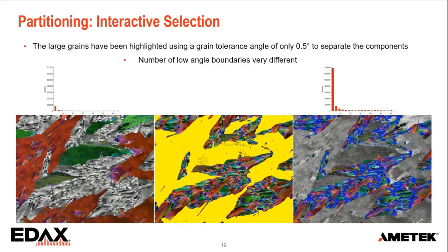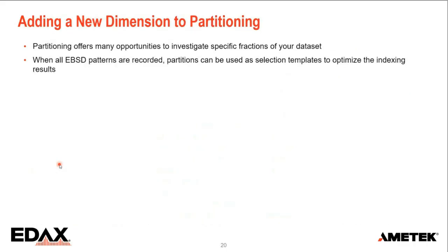And when you go to the larger grains, obviously we have much less interface length available, so also fewer boundaries. But if I scale that chart, you can see that the distribution really is identical. So in this case, there doesn't seem to be a real misorientation, microstructural difference between the very small grains and the very big grains. Probably if we go to a lower magnification, these bigger grains are their own feather structure. So this partitioning gives you a lot of possibilities to look at specific fractions of your data set.